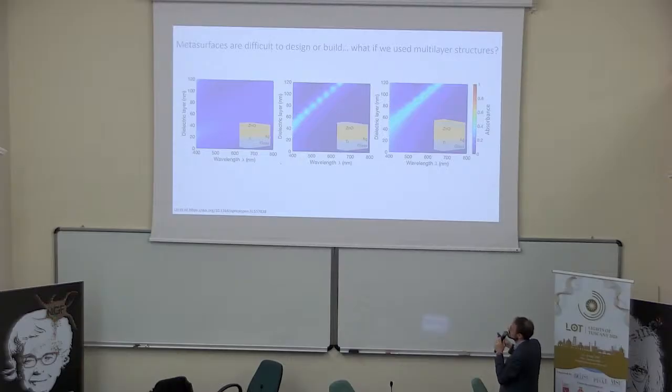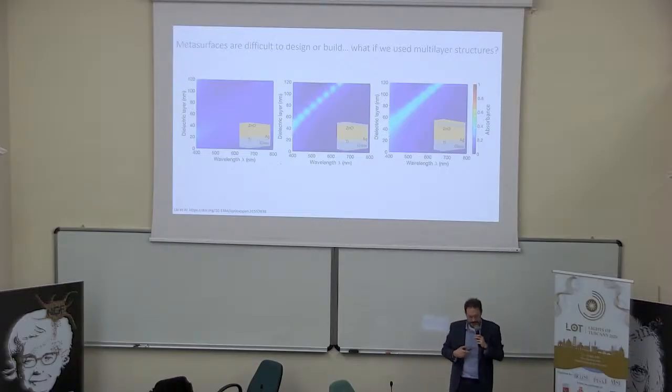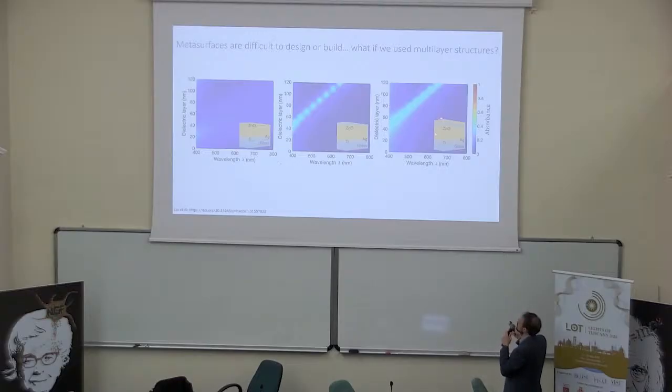But as you can see, it's not a continuum layer, because the last zinc oxide layer helps to get multiple effects from the better matching for the incoming wavelength. So we get a continuous band that allows us to design a material that can absorb different wavelengths as you want, just changing one parameter of your system.